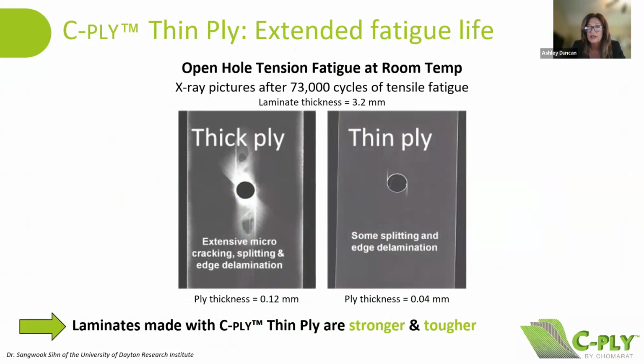This view graph shows the X-ray pictures of laminates with thin ply on the right and thick plies on the left after 73,000 cycles of tensile fatigue. The total thickness of both laminates is 3.2 millimeters. Notice only slight splitting on the thin ply laminate, the one on the right, around the open hole, and no delamination along the specimen outer edges or microcracking. For the thick ply laminate, which is the one on the left, there's massive delamination around the open hole and outer edges, plus microcracking along all of the plies. So in summary, the laminates made with the thin plies show resistance to both microcracking and delamination in that study.